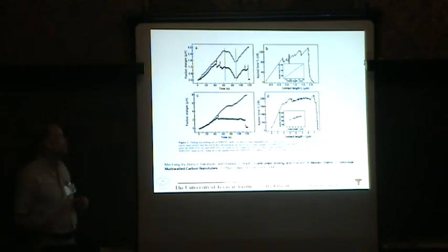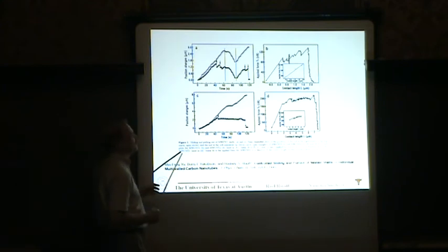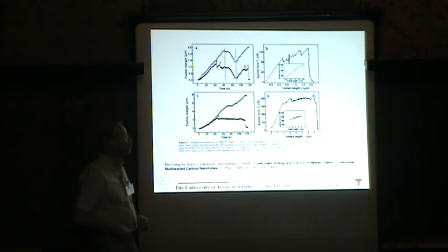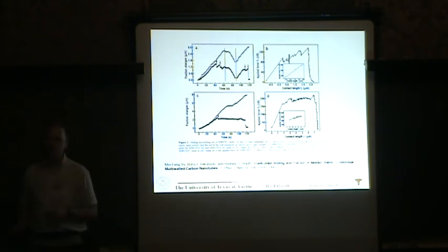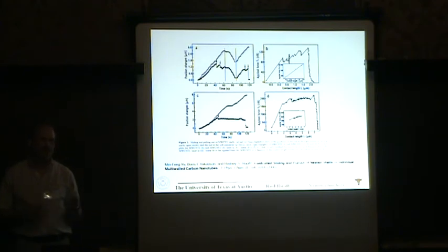One tube had a force versus contact length between the outer shell and the inner shell, which was sensible in terms of the range of shear strength values for graphite that ranged from about 0.2 to 0.7 megapascal. And this value was around 0.5.